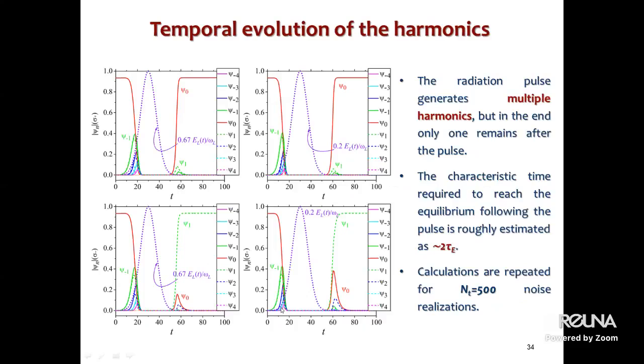Here, these figures show the temporal evolution of the order parameter harmonics. So you see here a few harmonics from 0 to 4. Of course, I used from -8 to +8 harmonics in the numerical simulation, but in order to show it on the figure, I present only from 0 to -4. We see that the radiation pulse initially excites multiple harmonics. However, only a single harmonic survives after the pulse.